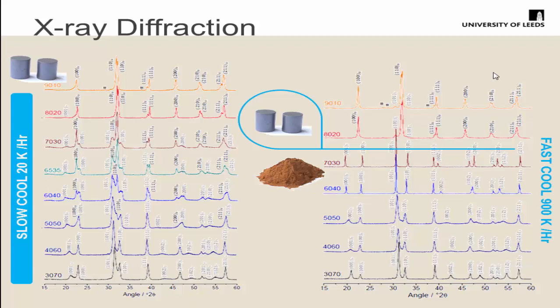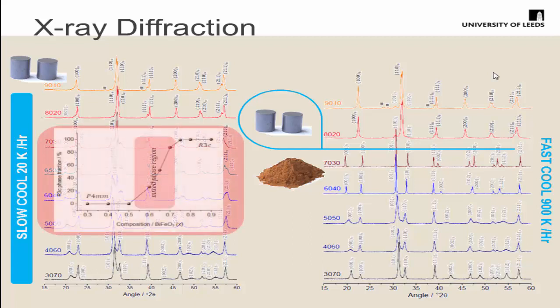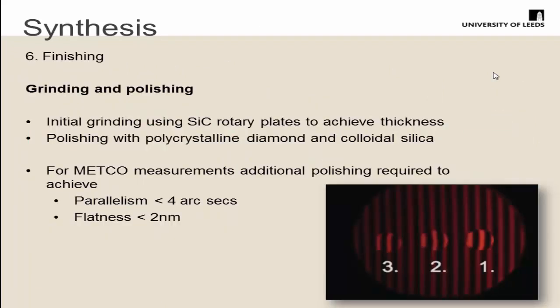This is demonstrated quite nicely when you look at the diffraction plots. Just by changing composition, and then changing the cooling rate, we can see we can make fully-dense ceramics with a range of crystallographic phases by changing composition. By changing the cooling rate, we can do the same thing but much more abruptly — we can really induce strain-driven transformations in these materials quite readily, and that really affects our high-temperature properties. This is a plot simplifying the phase fraction versus composition for the materials depending on composition at slow cooling rates.